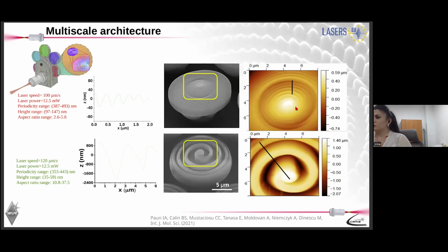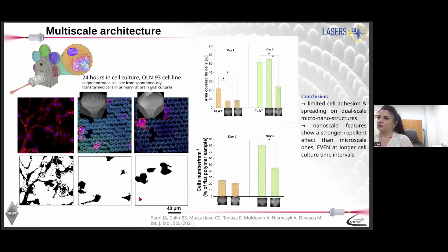It shows you better the nanostructures on top of this mushroom, which is easily given by the fact that our voxel has a spiral-like fashion inside the photoresist to polymerize it. And here you have the microstructure compared, micro with nano, numerically from atomic force microscopy images. We cultivated cells on these two substrates, microstructures and micro plus nanostructures. So these are the hierarchical structures. Both of them were good in repelling cells, but the best was still the microtopography decorated with nanotopography on top. So we have a hierarchical topography here. It shows the best results in what concerns the capacity to repel cells.